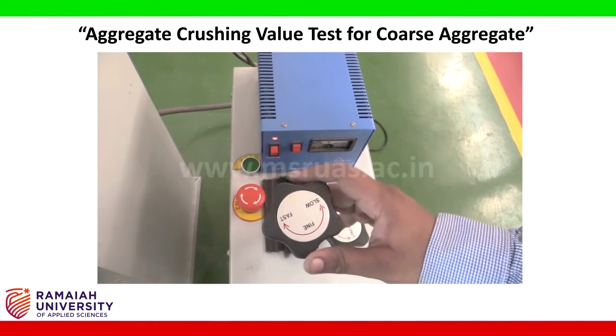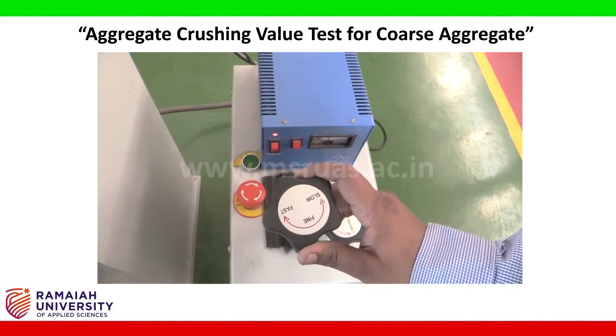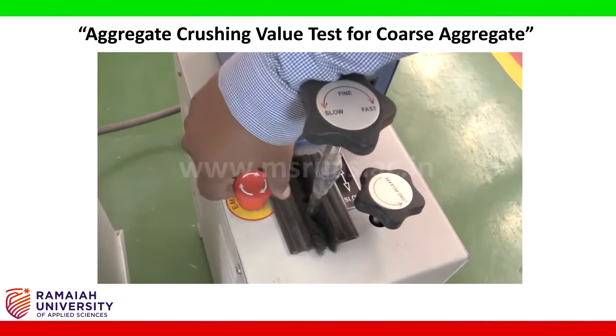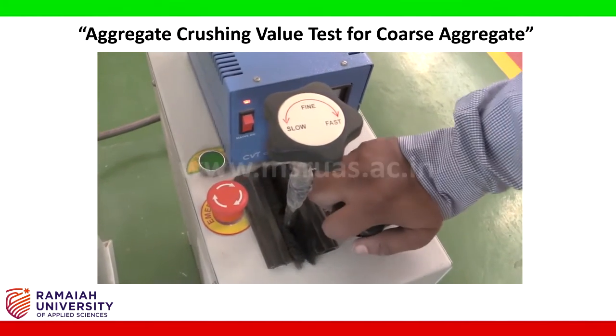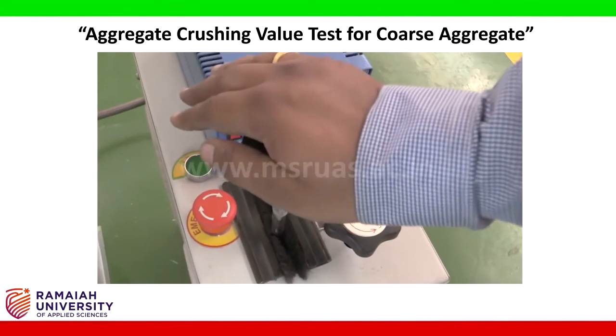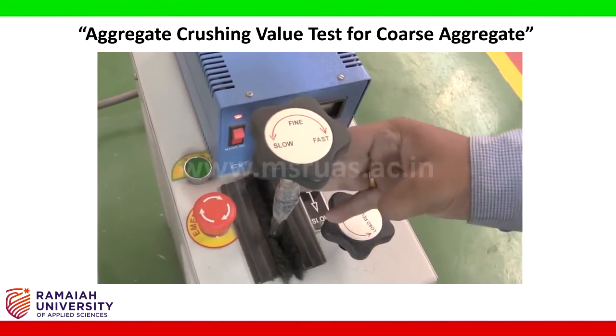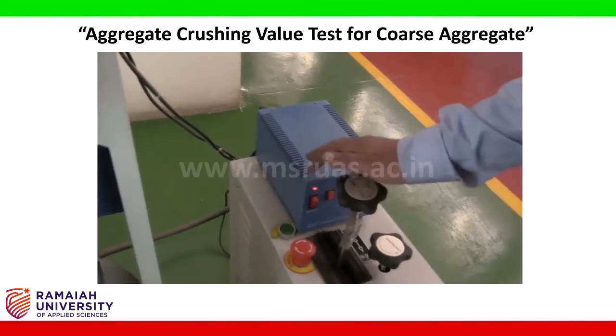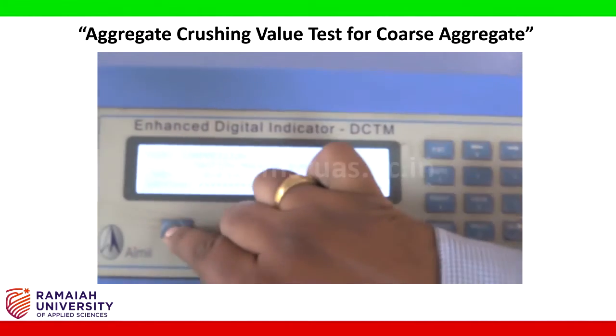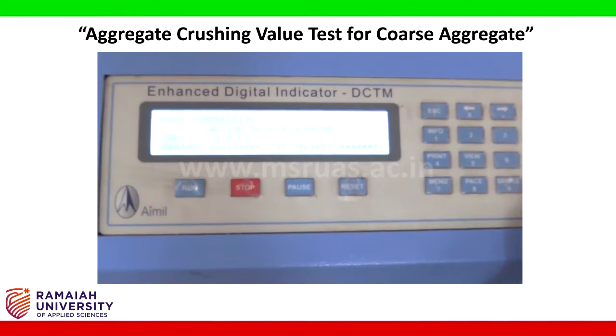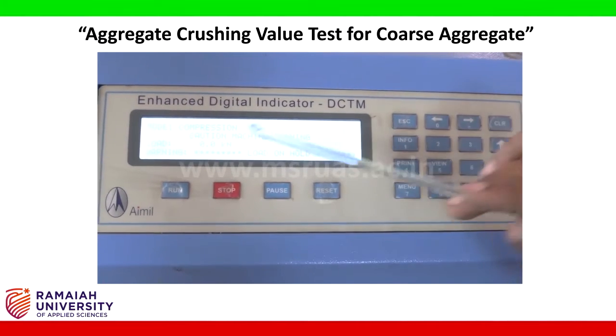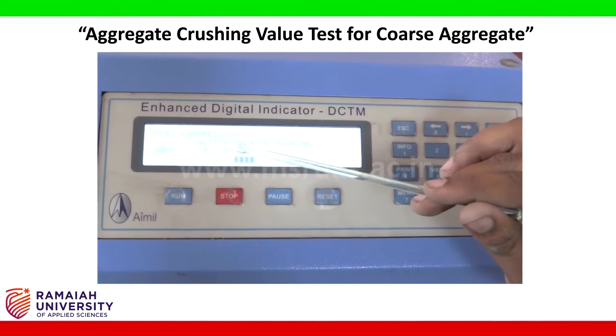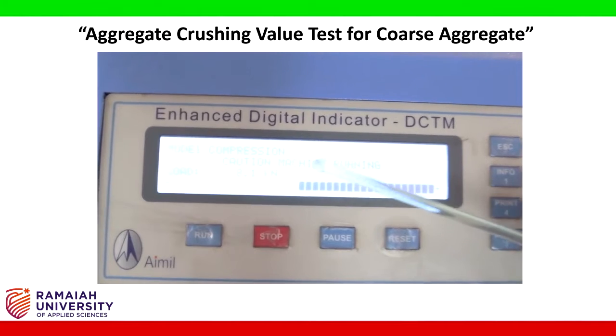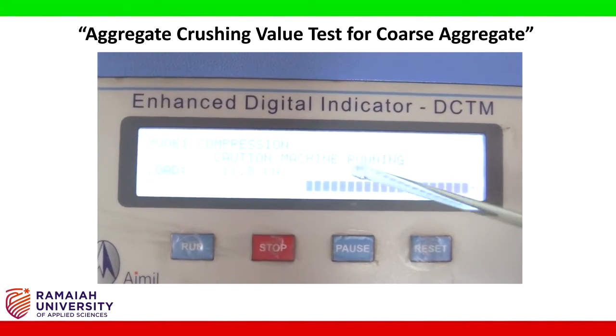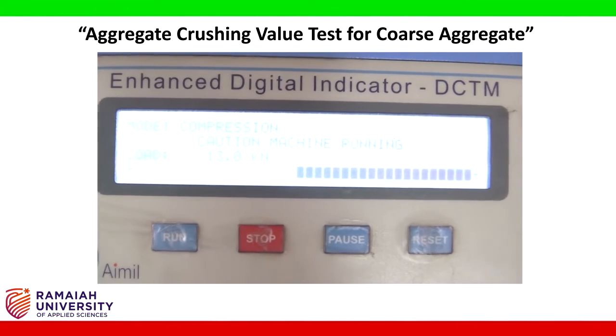For this particular experiment, we are supposed to do the rate of testing at 4 tons per minute. I release the emergency button. I am locking the load and fixing it to the neutral center. It's neither fast nor slow. And then we are going to run the machine, and we'll make sure that the load is 400 kilonewtons. At 400 kilonewtons, we are going to stop the machine.